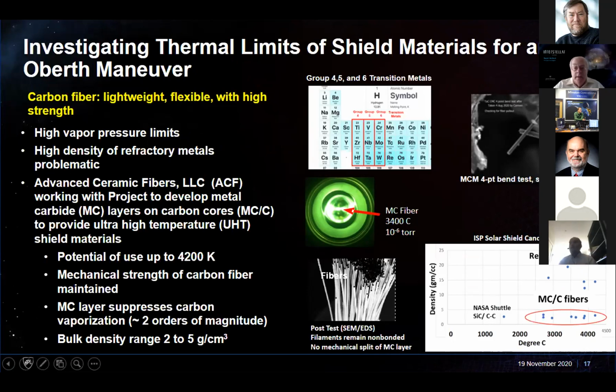You have a structure where the material system that you're building up is still really acting as a composite. So there's a matrix, there's a fiber, and you can see in this case they're pulling these parts out, and you're seeing that there's still fibers in here, and there's still a matrix in here. So you're still seeing that composite structure that is giving you some flexibility, and you're doing all this in such a way that we are taking carbon as a material up much higher than it would otherwise be able to go, at a density range which is in the range of possibility.